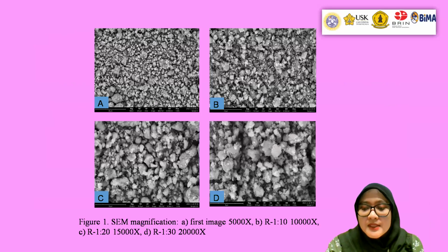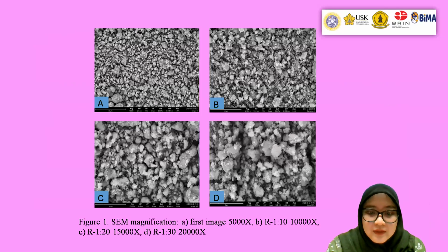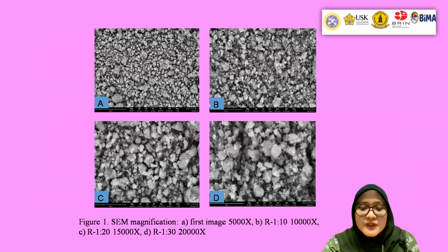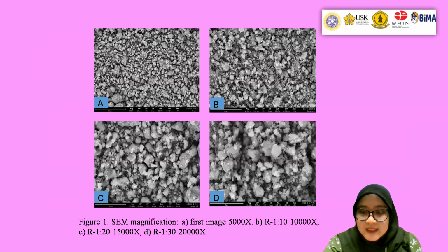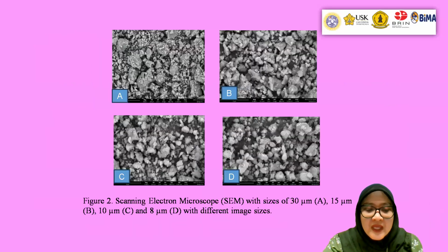And then you can see in the results that A, B, C, D, the first image is 5,000 magnification. And then B is 1 between 10, 10,000 magnification. And C is 1 between 20 in 15,000 magnification. And D is 1 between 30, 20,000 magnification. And figure 2 is a scanning electron microscope with different images: 30 micrometer, and then 15 micrometer, and then 10 micrometer, and 8 micrometer.